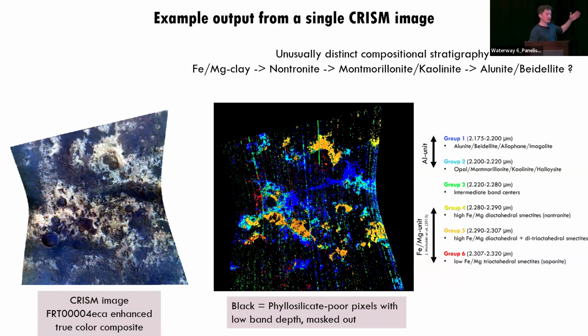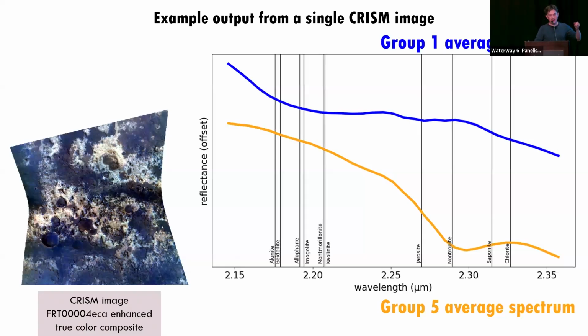And actually, this particular scene caught my attention because it seems to have, beyond just the ordinary aluminum and iron magnesium unit distinctions, there might even be some finer vertical zonation where it seems to grade from like an iron magnesium clay to a nontronite, then to things with band centers like montmorillonite or kaolinite, and then finally to things with slightly shorter band centers, which could be consistent with like alunite, halloysite, or allophane. And the code extracts an average spectrum from all 6 of those classes for all of these CRISM cubes.